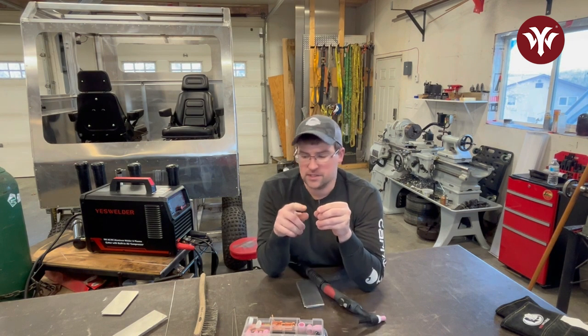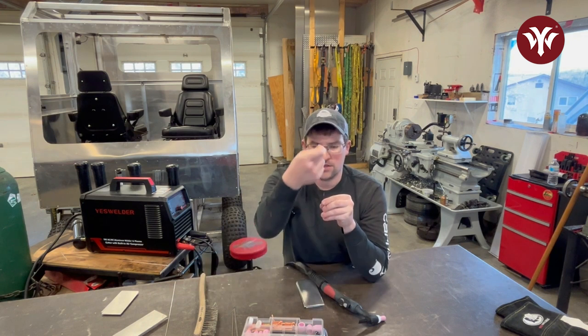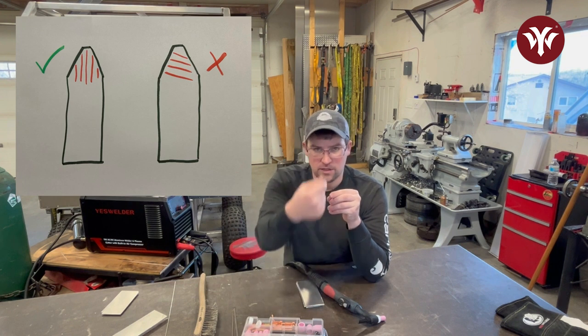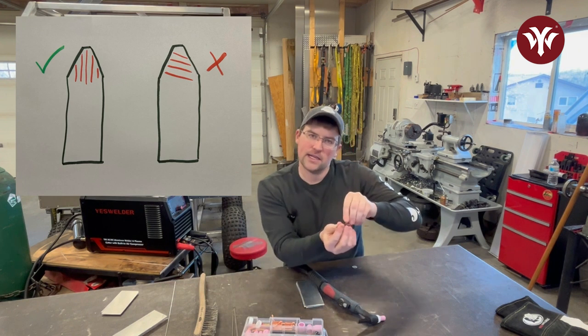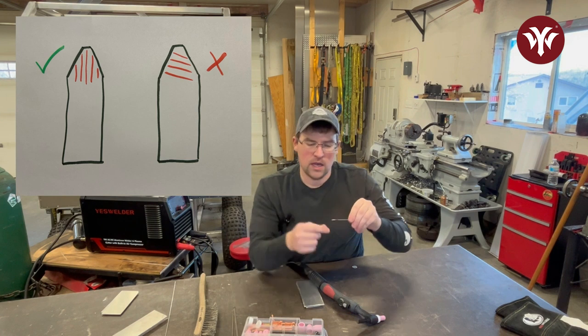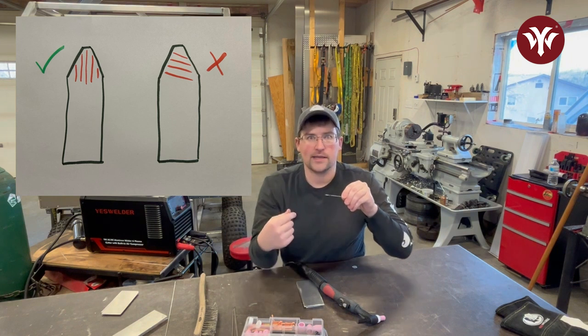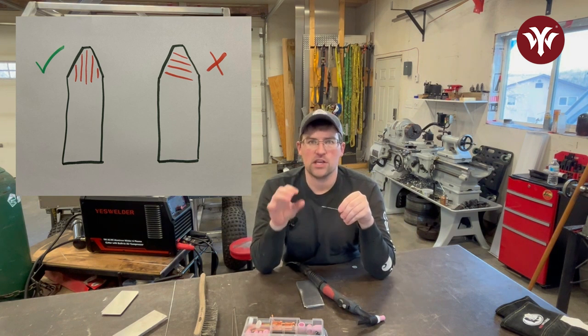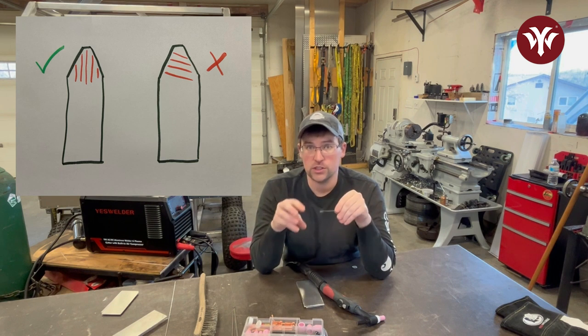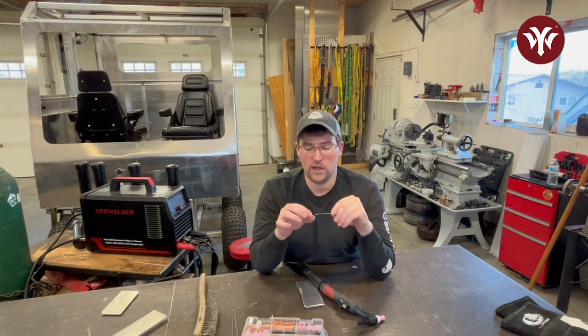So when you're grinding your tungsten, you always want to be grinding it so that the grind lines are parallel to the length of the tungsten itself. If you're grinding it sideways on your grindstone, you're going to get swirled grind lines, which is really going to mess up the arc. And it's all about having a really good quality arc to get a really nice weld.